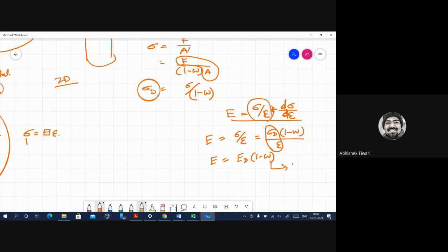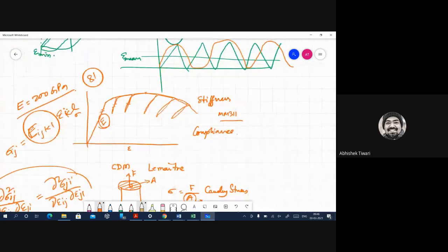So this omega is the damage parameter, and this starts from 0, meaning no damage, and goes to 1, meaning the complete failure has happened. So when this value will be increasing, this value will be decreasing. And when this is decreasing, then the net elastic modulus is actually decreasing, right? And this is why you have the slope which decreases with time, with deformation, with damage. So damage starts somewhere here, let's say. So before that, omega has a value of 0. So E is equal to ED. And once you start going away, so once the damage has started, omega has increased from 0, is higher than 0, and it is lower than 1. So I should write it like this.